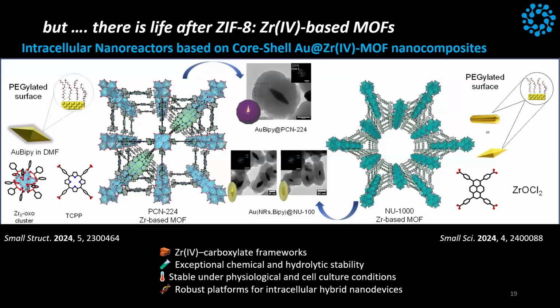Okay, but then Manuel Ceballos is a postdoc now in my group, but he did the thesis. He came and had the challenge to make the core-shell systems, and he has actually succeeded. I will briefly talk about this zirconium MOF. So basically, Manuel can make nanoparticles, bipyramids, rods, stars, any gold nanoparticle or magnetic nanoparticle. But the idea was to work on the surface to try to have some kind of interaction, either by the linker or the metal cluster of the MOF, to promote the crystallization of the MOF on top of the nanoparticle. And he has tried a lot of different things. Everything that is in the literature.